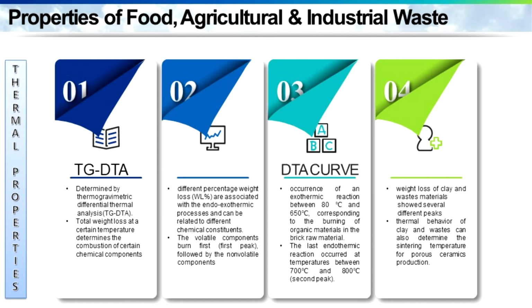Meanwhile, a longer early stage degradation was observed for sawdust, grape seeds and cherry seeds, where moisture evaporation occurred between 20 and 200 degrees Celsius. Interestingly, these findings can be further supported by the complementary DTA. A typical DTA curve would show the occurrence of exothermic reactions between 80 and 650 degrees Celsius, corresponding to the burning of organic materials in the waste.